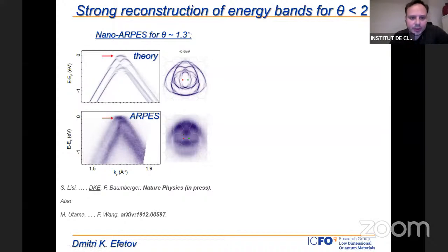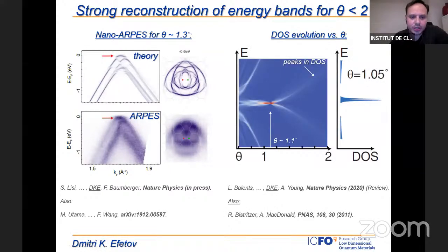Okay, and this renormalization is continuous as a function of twist angle. Here we have done some calculations to demonstrate this, where we plotted the density of states of twisted bilayer graphene as a function of twist angle. What we typically find is that when the twist angle becomes lower than 2 degrees, the Van Hove singularities, approaching 1.1 degrees, sort of diverge from each other.